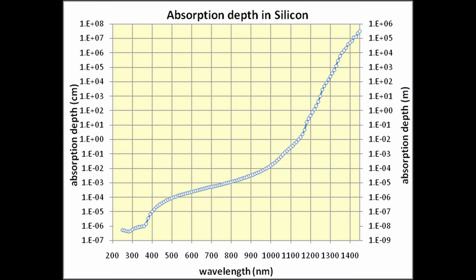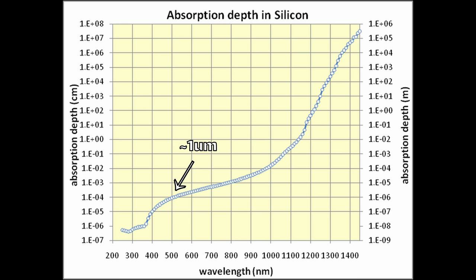There's a lot of nuance to this technique. The very first variable is what laser you're using. I'm using a fiber laser that is near infrared 1064 nanometers, which is not ideal for this case. The optical penetration of this wavelength into silicon is rather deep, several microns, which means a very large region of the silicon is melted each time a laser pulse hits it. Industry tends to use green or more often UV or excimer lasers because then you can keep the melt zone to just a very thin sliver at the top of the wafer like tens to hundreds of nanometers.